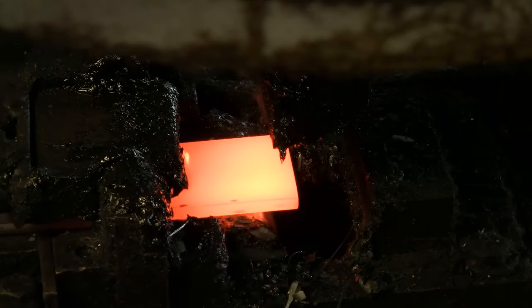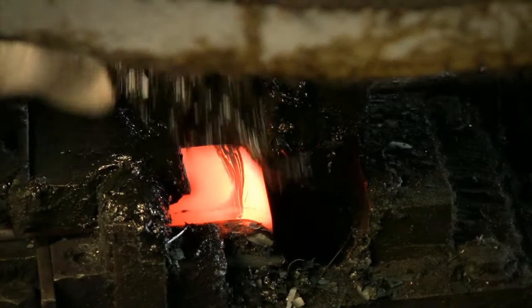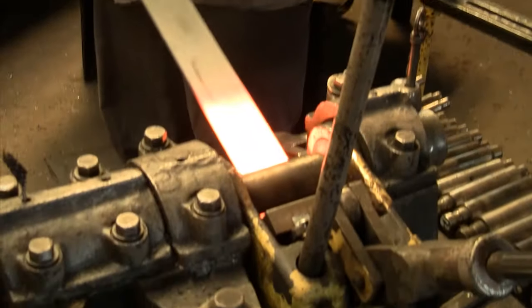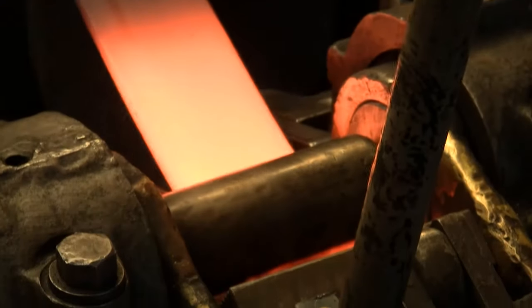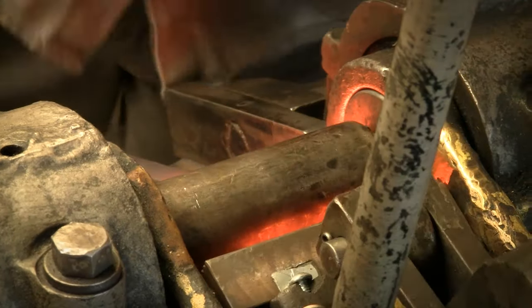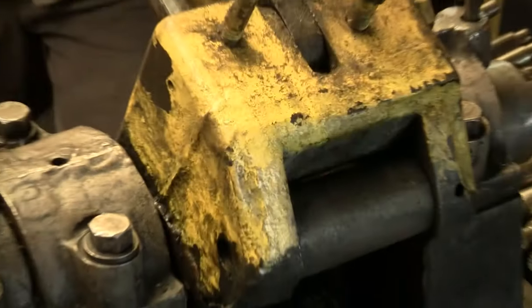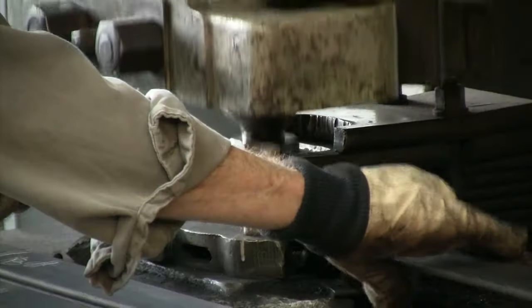The process at the eye forming machine is: the end is heated, a scarf — about a 45-degree angle — is cut on the end of the plate. The plate is then reheated and put into the eye machine, where a roller rolls the eye. The purpose of the scarf is to allow the end of the steel plate to tuck right in and make the eye perfectly round.